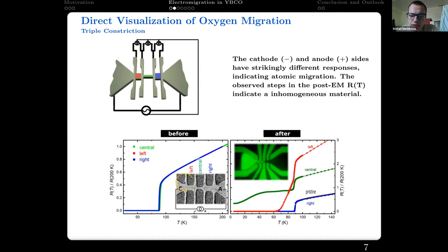As you can see, these curves are all normalized, so that you can see that before electromigration, our whole device behaves as a monolithic structure. But after we perform electromigration, this changes significantly. The right side, the anode side, here indicated in blue, does not change from the pristine state, while the central and left sides, that is this and this, change, with the central bridge losing superconductivity completely and the left having a smeared out transition. Notably, both of them